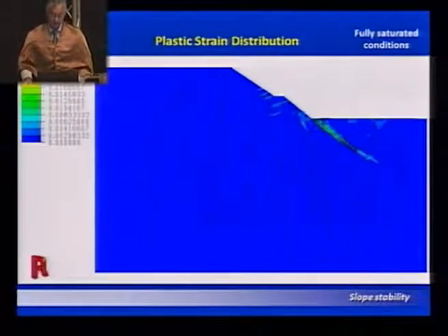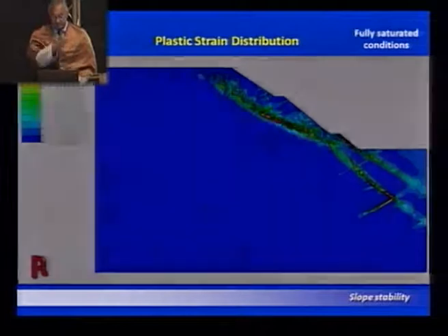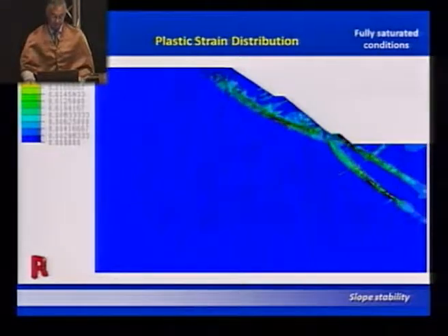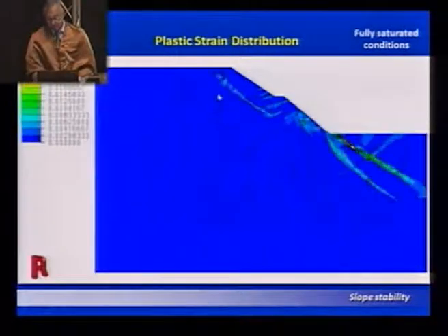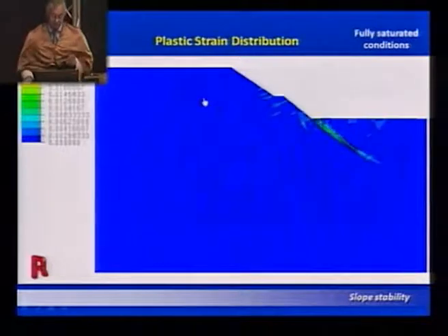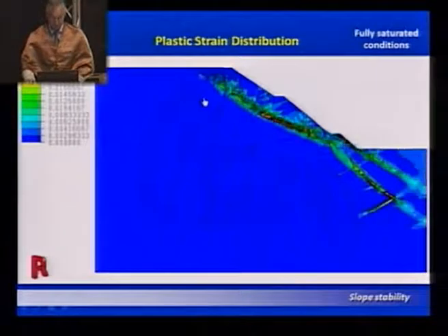This is just a block of rock, and we're putting the main fractures directly into the model, and now we're going to excavate these in a series of steps, 12 steps. And what you see, you get the classical slip line failure. You also get a series of fractures occurring throughout. You get fracture occurring in the shear band here and also on the surface. So we have a mixture there of continuum behavior and discontinuum behavior.